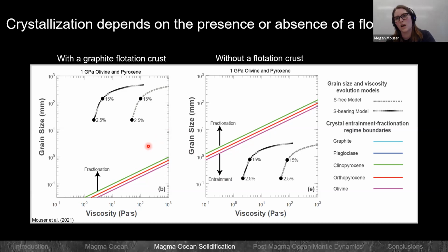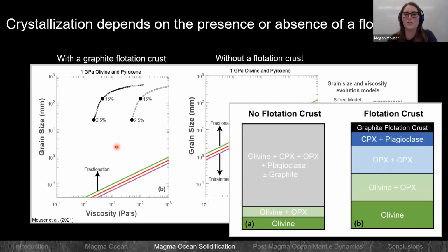So in regards to the different types of flotation crust, if you have a thinner flotation crust, you'll probably be closer to the boundary between fractionation and entrainment. If you have a thicker crust, you're going to be further up into this fractionation regime. So that's kind of how it would look with that scenario. But again, we're just going with the fractionation here with the 1 kilometer thick graphite flotation crust. So just to put it in simplistic terms, if we don't have a flotation crust, we would expect something that is primarily homogeneous in composition. But if we have a flotation crust, we could expect a fractionally crystallized mantle where we're developing these compositionally distinct horizons within the mantle.